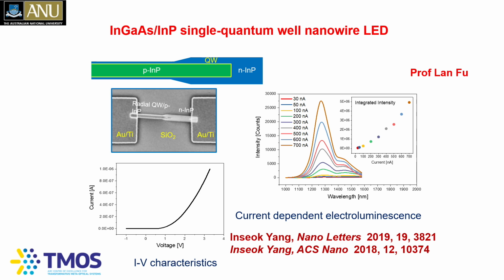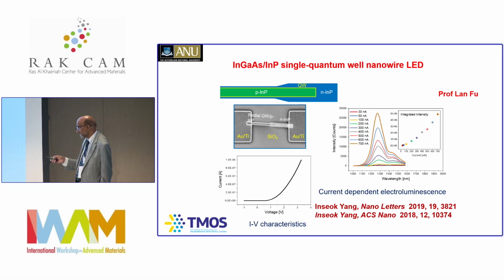So that's why you end up getting two emission peaks. But you do not see any narrowing of the line width like in a laser. You also don't see any threshold-like behavior, indicating that they're acting like nanowire LEDs rather than lasers. So you ask the question, why? You've got a PN junction, you're able to inject current, and you should be able to get the lasing.